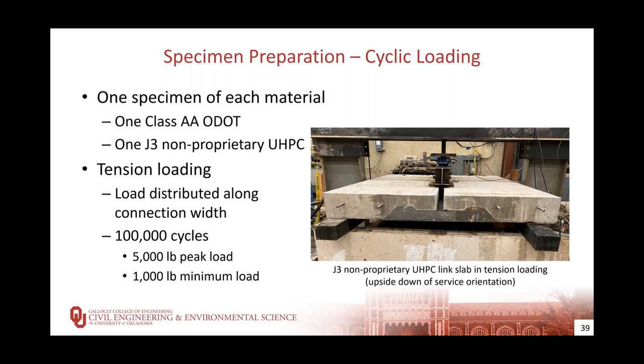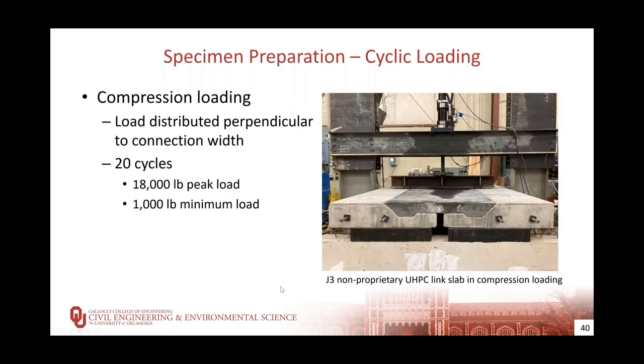We flipped the specimens to test the connection surface in tension, the most critical loading. For this test, the specimen was supported at its four corners and a steel beam was placed along the gap to distribute the load along the link slab length. The specimens were subjected to 100,000 cycles from 1,000 pounds to 5,000 pounds and back to 1,000. The cycle count was determined so we could get enough loading to damage the specimens if they were going to damage. After tension loading, the specimens were then flipped back over for compression tests.